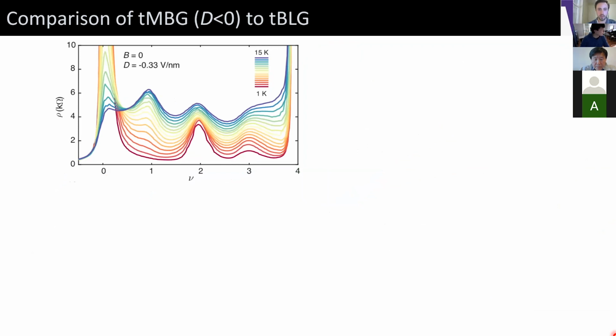The more interesting one is what happens when we look at the D negative side, which should be roughly analogous in our cartoon picture to twisted bilayer graphene. In this case now, we don't actually have correlated insulating states. We have what I'll call correlated metallic states, where we have these resistive bumps at quarter filling, but the resistivity shrinks for all of these states as we lower the temperature. And in fact, some of them even completely disappear. So at quarter filling, we see this state at high temperature, but it's gone at low temperature.